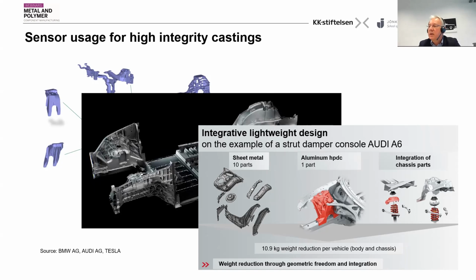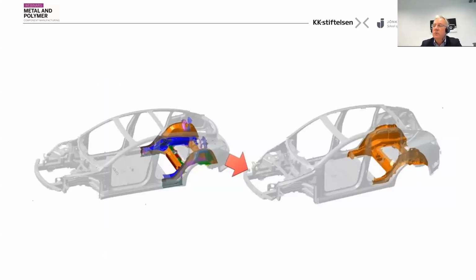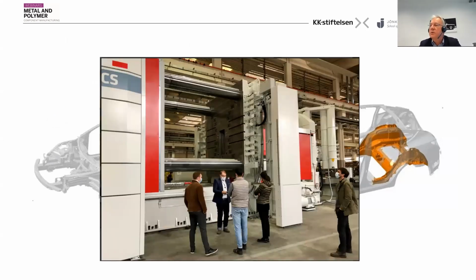Here you can see high pressure die casting gives you a weight reduction of 10 kilograms per car. That's huge. And this is just a very new picture. I just added it because it shows the new Tesla. The old one on the left side is 70 parts, and he is going to substitute it with one part. And what you need to do this, of course, is a huge machine. Anders already mentioned that it's a 6,000-something ton machine, and it's very huge. Tesla ordered the first machine which has more than 6,000 tons of locking force. That's crazy, but Elon Musk can do it.